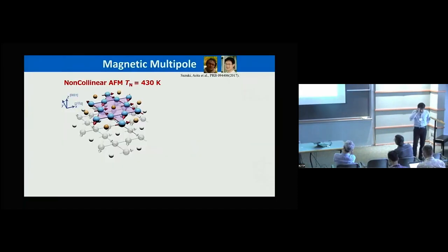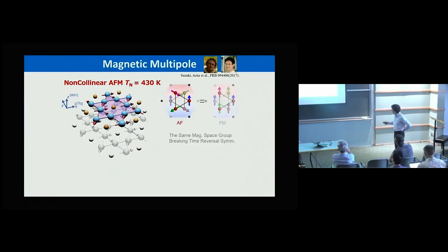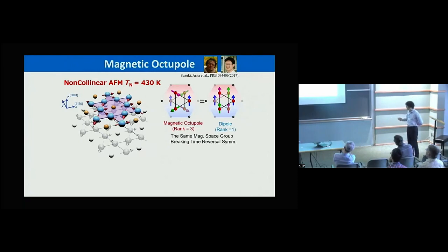So let me just go through the notion of the cluster magnetic multipole. If you do this multipole classification, of course the collinear phase is the most popular one, which is the simple dipolar one. But it turns out this cluster, this anti-chiral 120-degree order on this particular Kagome lattice, shares the same time reversal symmetry, the magnetic space group. And of course, this doesn't carry magnetization, so rank 1 is not available. And there's spatial inversion symmetry, so rank 2 is not available. So the minimum rank available is an octupole.